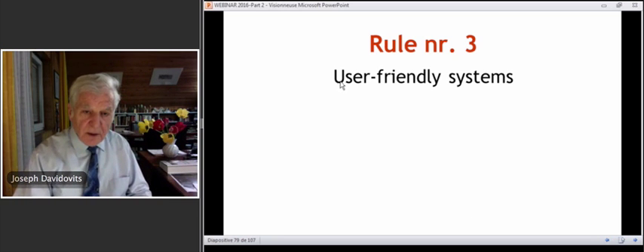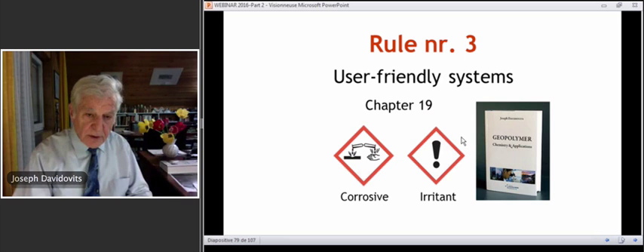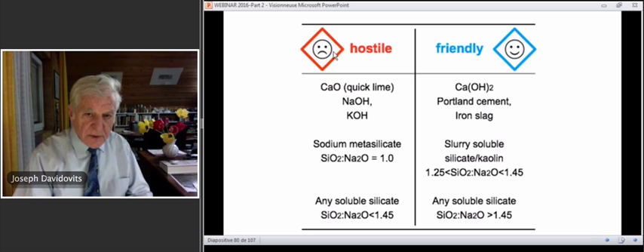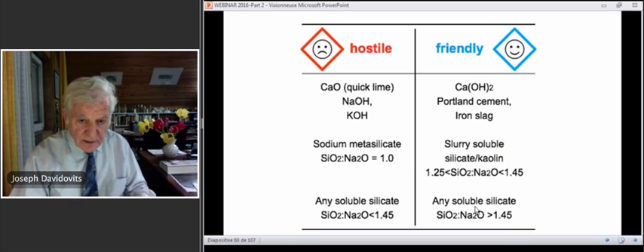Rule number 3, user-friendly systems. Chapter 19 in my book. You have in chemistry what is called corrosive and what is called irritant, and what we call hostile systems and friendly systems. Quicklime, NaOH, KOH is hostile. Slaked lime, Portland cement, iron slag is friendly. It doesn't burn. You can handle it by hand. Sodium metasilicate is hostile. A slurry of silicate and kaolin is friendly, and any soluble silicate with a molar ratio higher than 1.45 is also friendly.